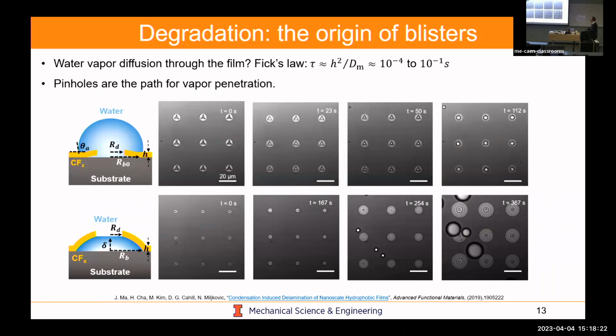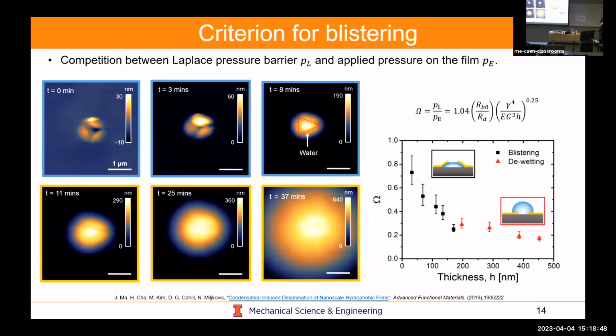So if we look at an interesting result, what we notice is that if we have bigger size pinholes, so these are larger than the ones I'm showing you down here, you actually don't see blister formation. You'll have water droplets nucleate, and they will actually grow up and above the coating. If they're small, what will happen is they'll actually form blisters. And you can actually clearly see this here. And this test was very interesting because we first thought, why does this happen?